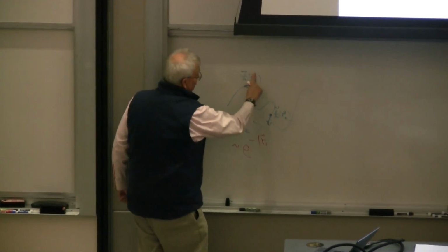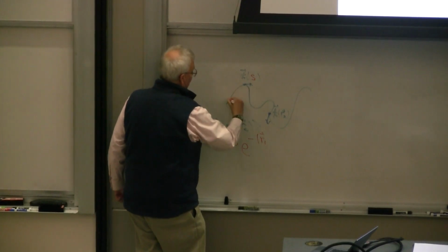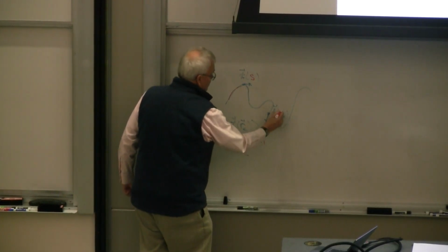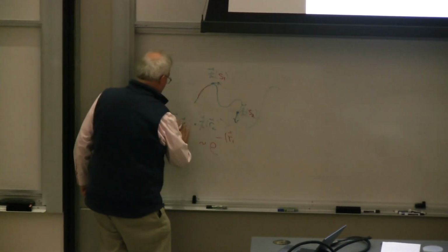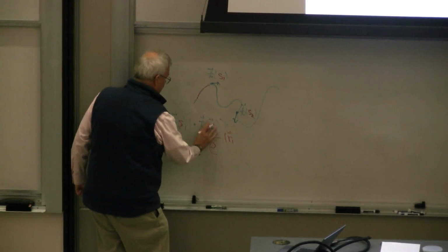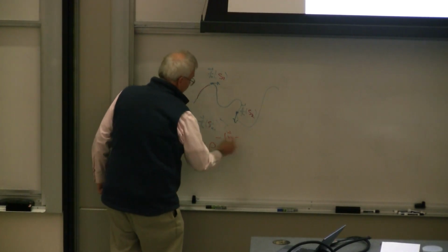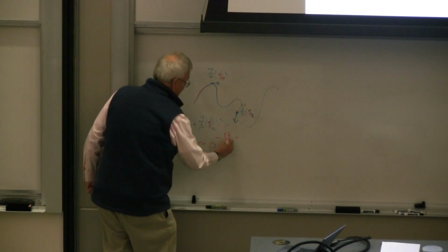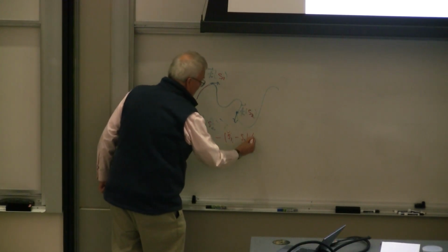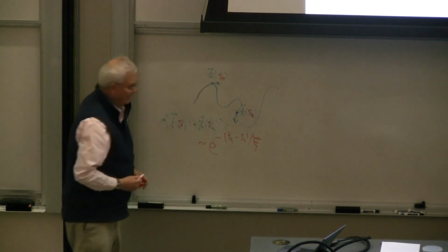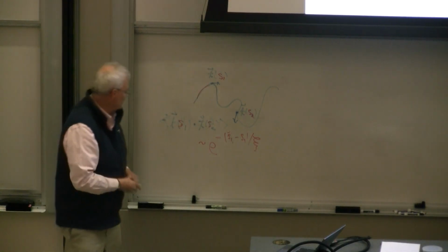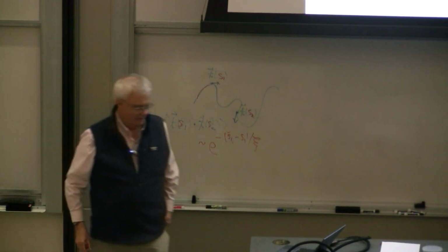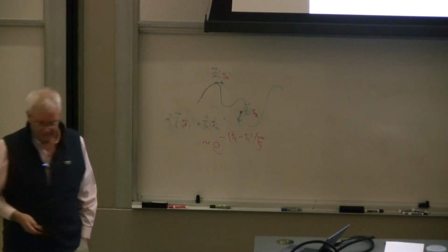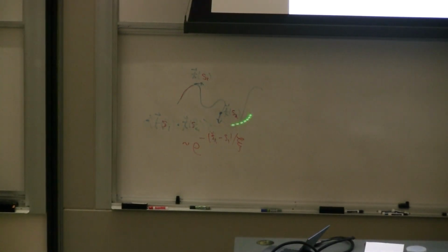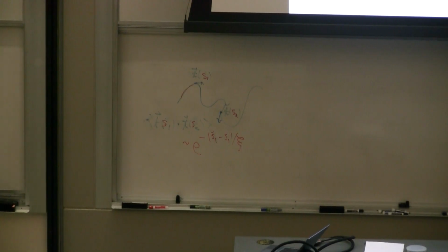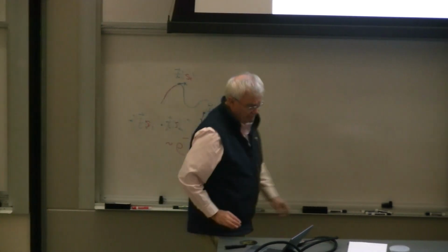In fact, you might want to just reparameterize it in terms of the arc length as you go along. So you go along a certain arc length. Here's another arc length at S1, S2. So you do this as a function of arc length. And this thing falls off like the difference between the two arc lengths, S1 minus S2, over some sort of persistence length. And this is nothing more than an embodiment of a famous theorem. It goes back to Landau in one-dimensional statistical mechanics that you can't have long-range order in some kind of one-dimensional system.